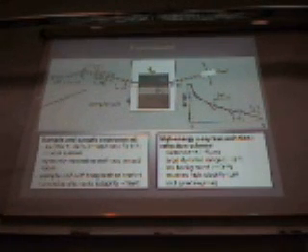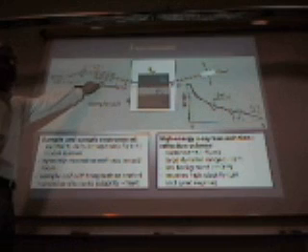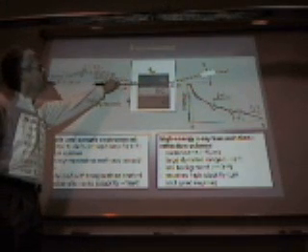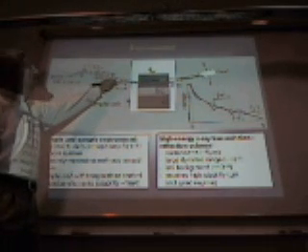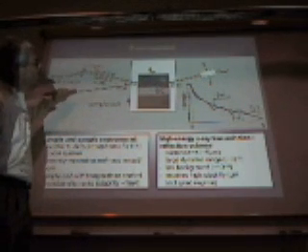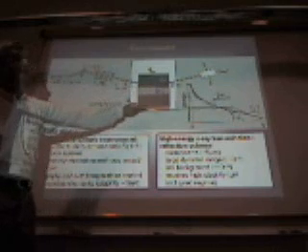Now if you have a layer developing in between with a different density, meaning a different index of refraction, then of course you're not only reflecting at this bottom layer here, but also at the top one, because there's another jump in the index of refraction. And these two beams interfere and they give you an oscillating structure like this. So this is the telltale signature that there's a layer with a different density. Yeah? As I said, it could still be melting, but if there is no change in density, we don't see it.